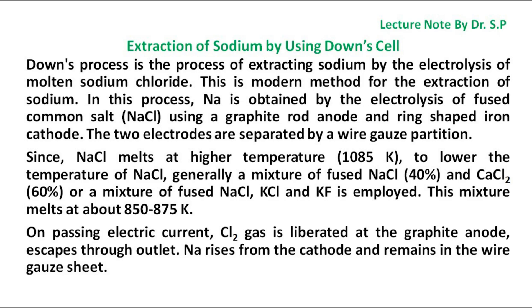Since sodium chloride melts at a higher temperature of 1085 Kelvin, to lower the melting temperature, generally a mixture of fused sodium chloride 40% and calcium chloride 60%, or a mixture of fused sodium chloride, potassium chloride, and potassium fluoride is employed. This mixture melts at about 850 to 875 Kelvin.